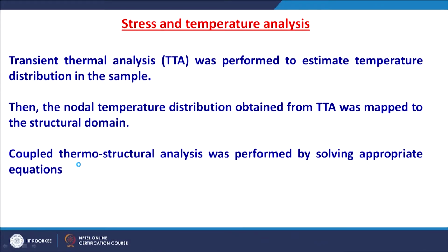Stress and temperature distribution were studied first by transient thermal analysis and then thermostructural analysis. Initially, transient thermal analysis was performed to estimate the temperature distribution in the sample. Then the nodal temperature distribution obtained from the transient thermal analysis was mapped to the structural domain, and then we have a coupled thermostructural analysis by solving appropriate equations. First, the results from the transient thermal analysis.